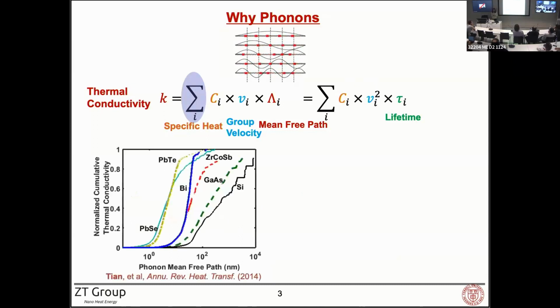For example, for a long time, we used a single number for the mean free path to describe the average distance phonons travel in a single material. That was 34 nanometers for silicon. But with the help of detailed DFT-based calculations, we were able to map out the mean free path distribution in different materials. As you can see, the mean free path distribution spans several orders of magnitude from nanometers to microns. And different materials have different distributions, which become the guidelines for nanostructuring to reduce the thermal conductivity for some thermoelectric applications.